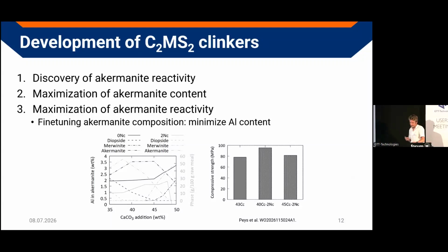Then there was still a little detail which we could fine-tune, and that is then the akermanite composition. We could fine-tune the reactivity of the akermanite by pushing away the aluminium from it. And this we did in a few different ways, but for instance, if you add a little bit of alkalis, then you form a little bit of nepheline and you drag your aluminium from the akermanite, which makes the solid solution with gehlenite a bit less, and then it makes the akermanite more reactive.